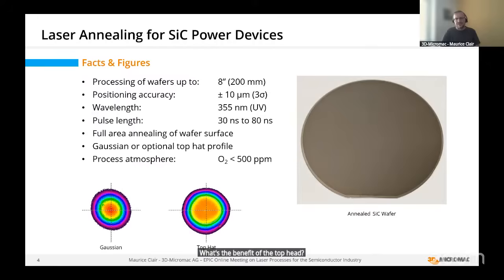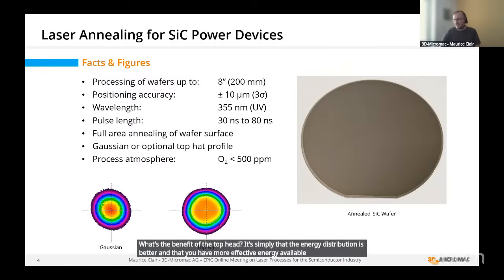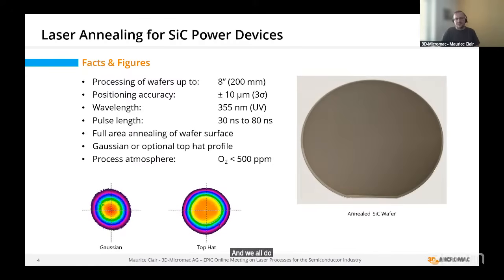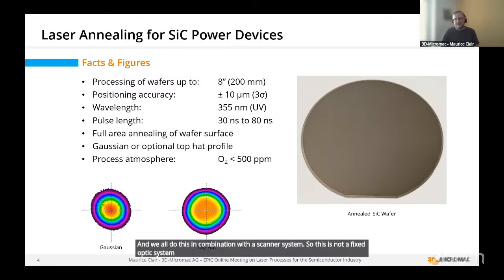It's simply that the energy distribution is better and that you have more effective energy available for the actual chemical reaction, because you don't over-exceed like in the Gaussian, and the uniformity of the layer is slightly better. And we all do this in combination with a scanner system. So this is not a fixed optic system. The sample is not moving, and we do this under a defined atmosphere of less than 500 ppm.